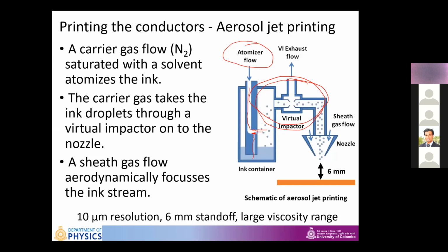Inside the nozzle, we use a gas flow, we call it sheath flow, to set the size of the ink stream. We call this aerodynamically focusing or defocusing the ink stream, so we can change the width of the circular ink stream. Below, at about 6 millimeters height, we have the platform where we need to print the circuit. We call that 6 millimeter distance the standoff distance. Usually the stage or the substrate that we need to print on is positioned on a movable platform where you can move it in X and Y direction. And in sophisticated cases, you can move the entire system in 5-axis and then print your required electronics in a coordinated motion pattern.